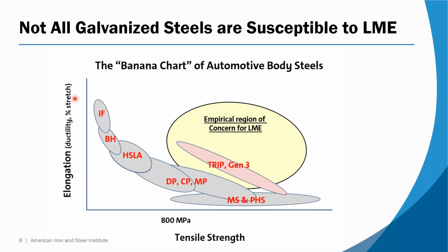We've all seen this banana chart showing the elongation and tensile strength of steels. What I did was add a new bubble on here for where we tend to see LME. It's not very scientific - these are just where I personally have observed LME. I've not observed it in these materials here, and I've not observed it in martensite and PHS, but when you get above 800 megapascals, that's when you start to see it happening at lower and lower temperatures.